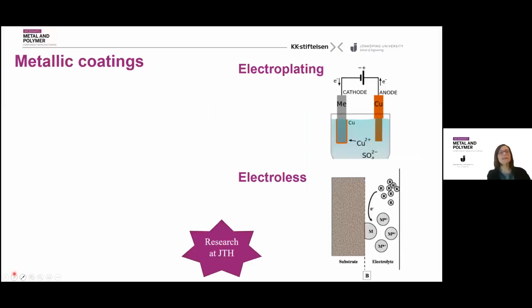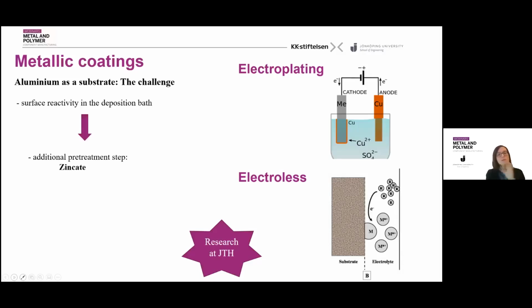Or you can add a metallic coating on it. You can do it by electroplating or by electroless, and you can choose any metal you need for your purpose. But you have to be really careful that when you work with aluminum, the challenge is surface reactivity. The deposition baths for electroplating and electroless are usually chemically aggressive, and aluminum is really reactive, so no matter what process you choose, your main attention should again be on the pre-treatment.